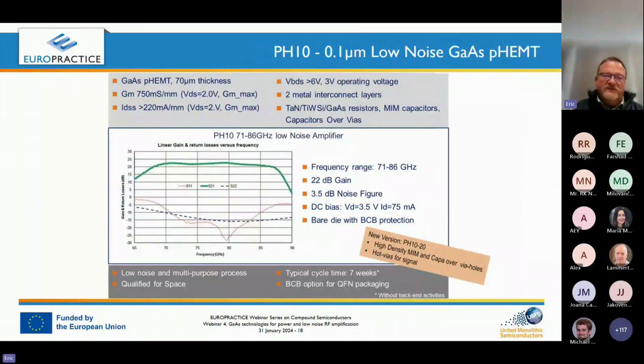So pH10, now what are the main performance and applications with pH10? pH10 is a low noise GaAs pHEMT process, 70 micrometer substrate thickness with a high transconductance, high current. Breakdown voltage is higher than 6 volts. So typically we bias the transistor at 3 volts. We have two metal interconnect layers, optional metallic resistance with different values, MIM capacitors and capacitor over vias and things like that. So here is an example of what we did. It's a UMS product on pH10. It's an E-band LNA, in this frequency band, 71 to 86 GHz, providing 22 dB gain with noise figure below 3.5 dB. The bias that I mentioned, this one is at 3.5.